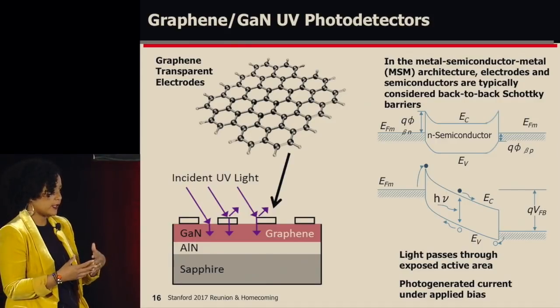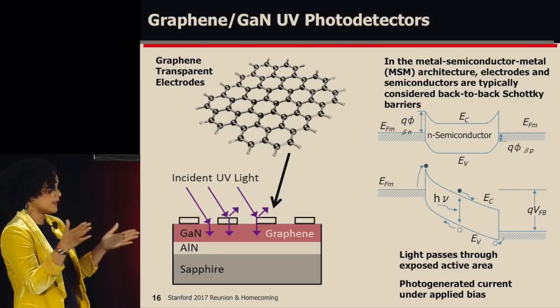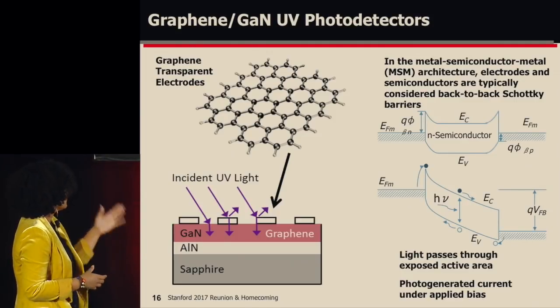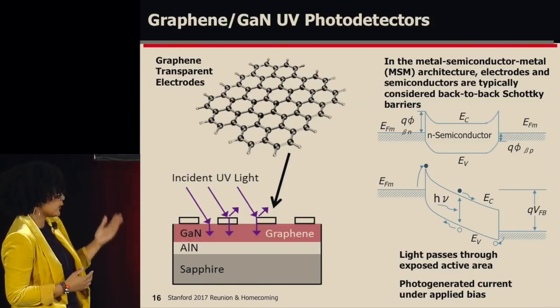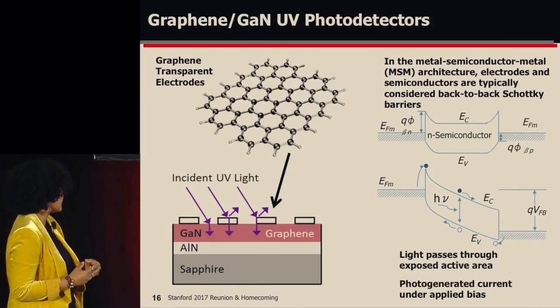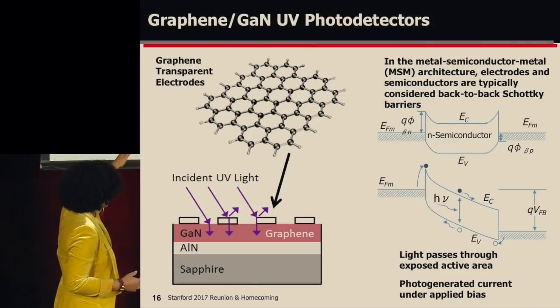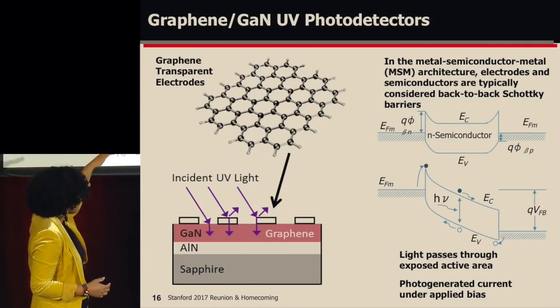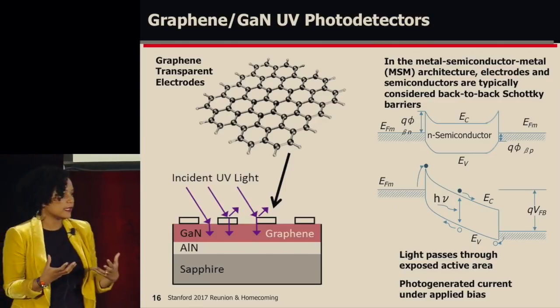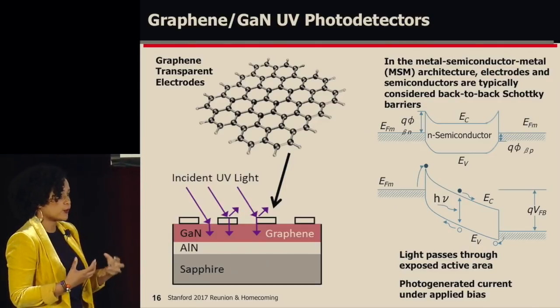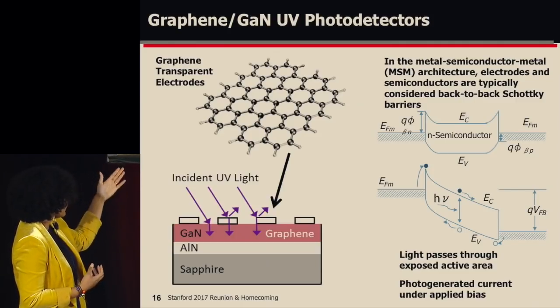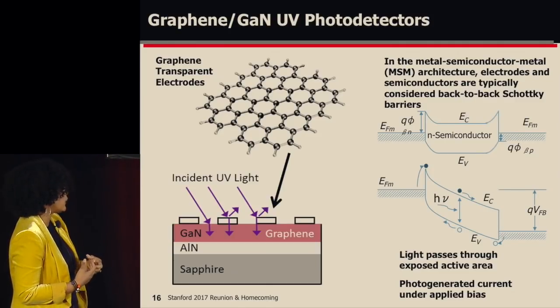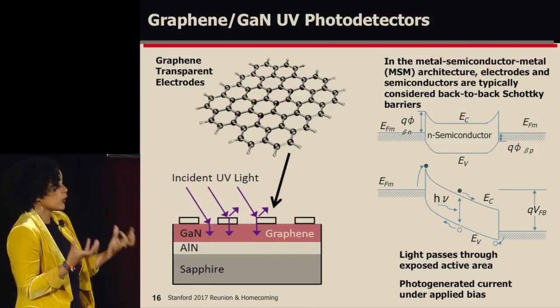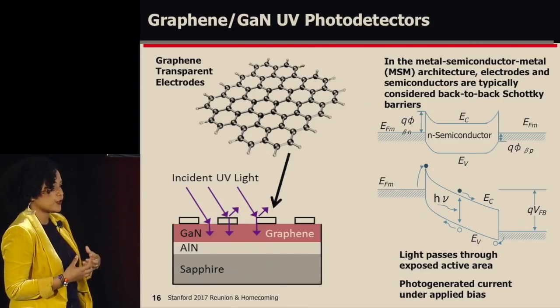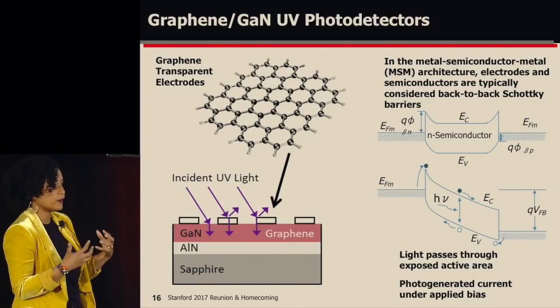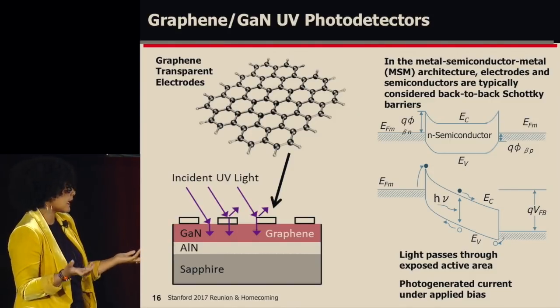It is a transparent material, and so it allows all of the optical spectrum to be transmitted. And so we've been using this as a conductive layer to develop ultraviolet photodetectors. So what we do is we transfer the graphene to our gallium nitride substrate. We do patterning, and then we create these interdigitated electrodes, which are conductive. And when we shine ultraviolet light onto this structure, what happens is we generate a current. And that current is proportional to the intensity of the ultraviolet light. And so we can use this as an ultraviolet detector.